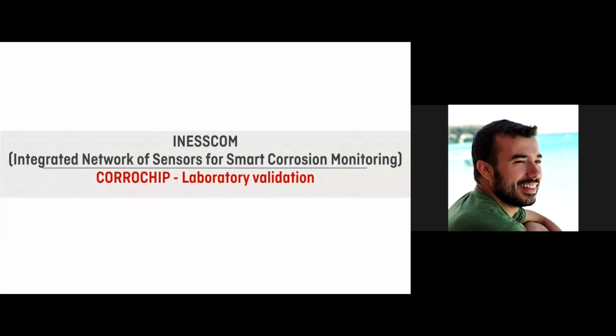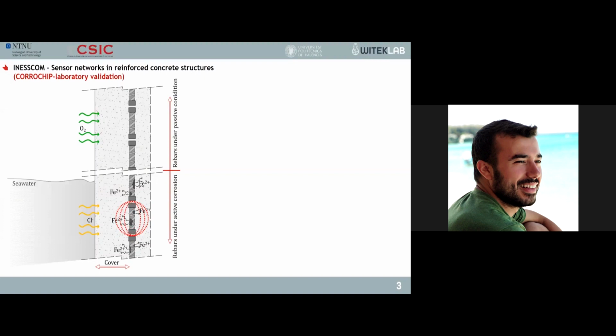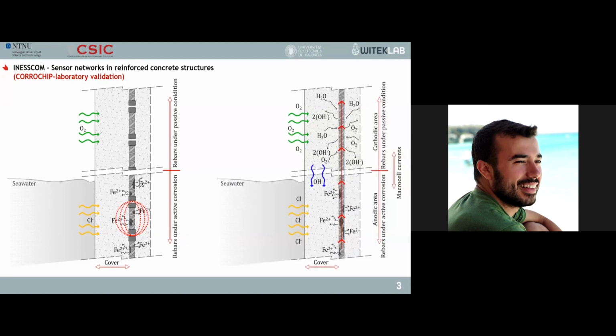First of all, laboratory validation. Often, the approach to sensors embedded in concrete is to introduce isolated elements on which corrosion is measured. However, this is a mistake, as the rebar, as Jose Enrique commented, in reinforced concrete structures is continuous and interactions occur between different areas due to different exposure conditions. These interactions are called macro-cell currents, and only when this is taken into account together with the micro-cell corrosion, for example, corrosion due to local conditions, can the real corrosion of a rebar be known.